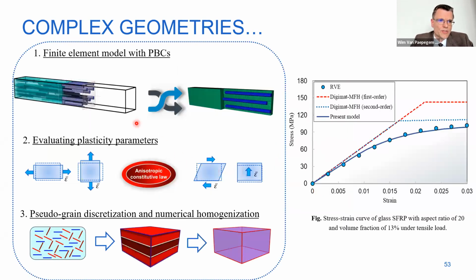How do we try to approach this? Again, with the same philosophy as what I showed before. We start with a representative volume element with short fibers, but here they do have a 0 degree orientation perfectly. So all the fibers are under 0 degree. And then we try to calibrate with these models an anisotropic plasticity law, which is a homogenized behavior. And then only we start to add the orientation effects and then go to the core shell effect, where the orientation in the middle is different than from the shells. And then we can treat it as a homogenized material.